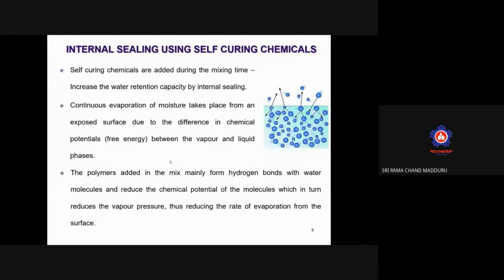When the mixing water is there, the ideal condition is that the mixing water is properly maintained. If you can avoid the evaporation of this moisture, then the water that is added during the mixing time can be helpful for proper hydration. In normal cases, there is a lot of pressure difference at the surface, and due to the chemical potential difference between the vapor and liquid phases, continuous evaporation takes place.